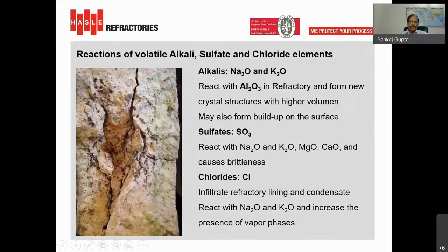Alkalis, basically sodium oxide and potassium oxide, react with the alumina of the refractory and form a new crystal structure with high volume. Because of that, you can see here, the refractory cracks when these alkalis react with the alumina of the refractory. And sulfates, which are coming from the alternative fuels, react with these alkalis and also react with the surface and matrix of the refractory and make the refractory more and more brittle and prone to failing in future.